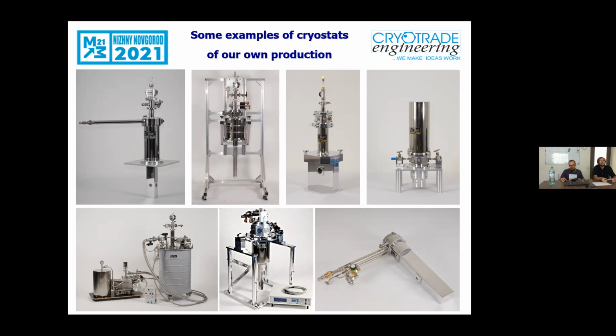You can see here is a cold head, and here you can see the vacuum pump and the helium system, which is providing cycling of helium inside the cryostat with throttling of it, and this allows one to achieve a temperature down to 1.6 K on a sample with a very small heat capacity. So 1.7, 1.6 one can reach if the application is with very low heat load. If the heat load is more, you can reach a higher temperature. But actually, one can reach 1.6 K in this system.